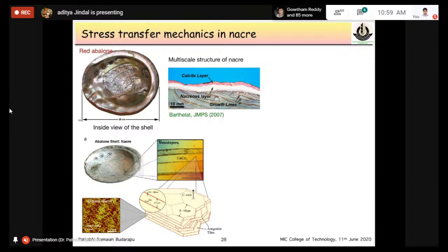Looking closely at the structure, the dimension or order of this picture is about a few micrometers. The tablet thickness is of the order of 0.5 microns, arranged like a brick mortar structure. A 3D view shows the bricks are hexagonal in shape, and in between the interfaces of the bricks we have the polymer material. It's 95% bricks and 5% polymer.